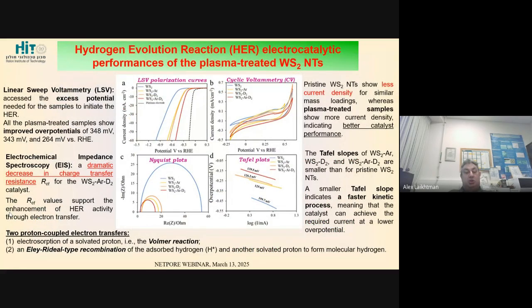So now going to electrochemistry, because this was the purpose of these experiments. This was performed by our colleagues from Ariel University. So there are several types of measurements. The most important is the first one, linear sweep voltammetry, which assesses the excess potential needed for the sample to initiate HER. The lower potential you have, the better the process. Of course, at a specific current density, we use the standard current density of 10 milliamps per square centimeter.